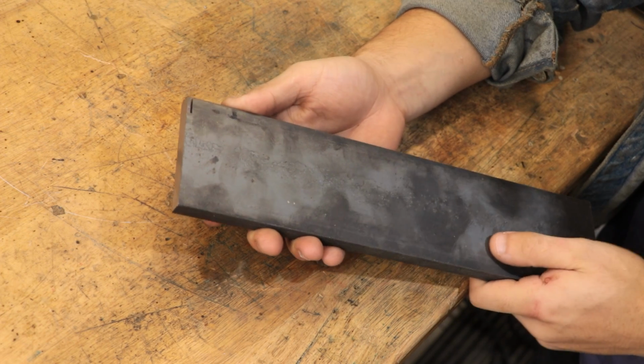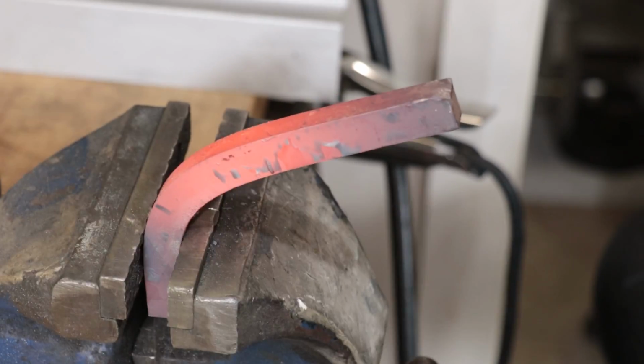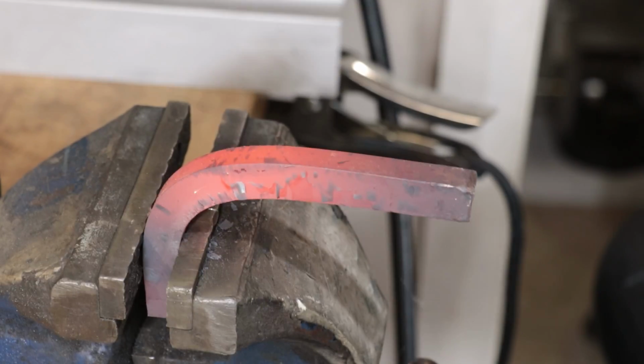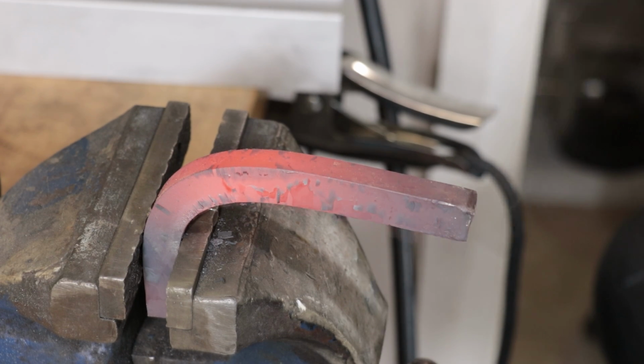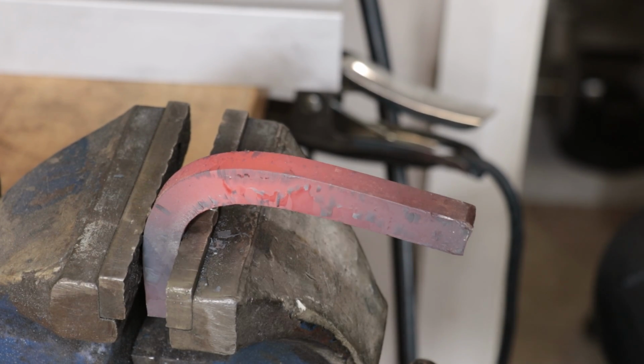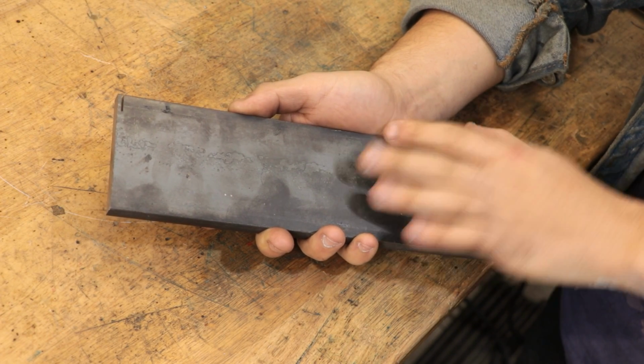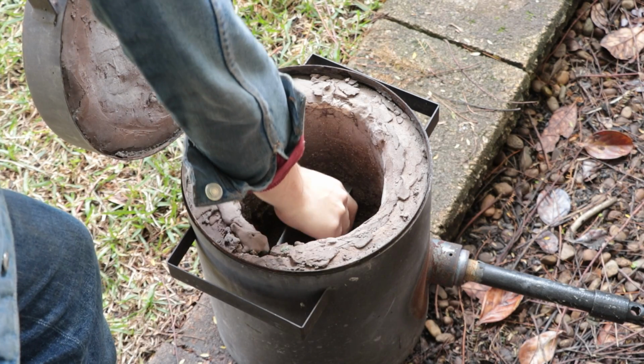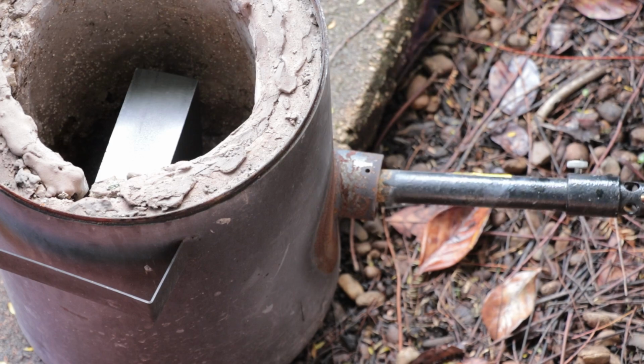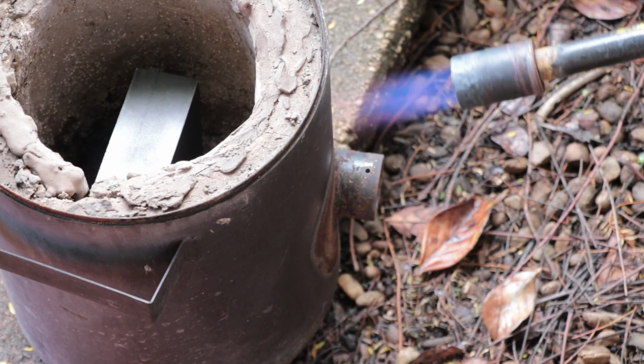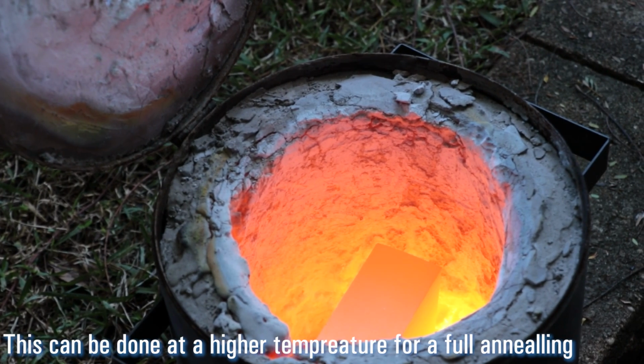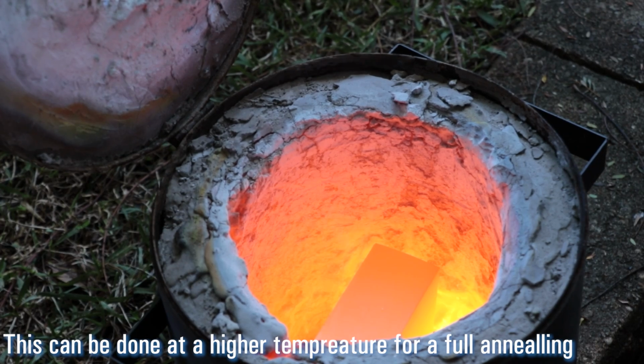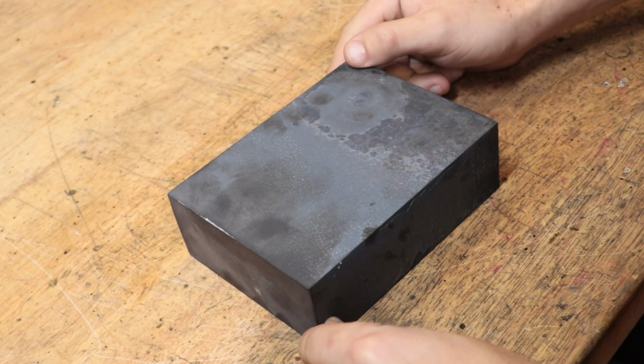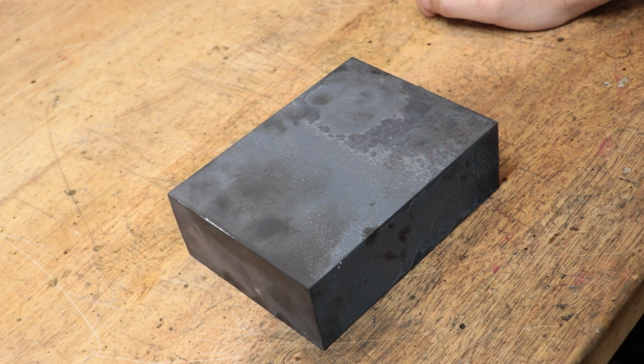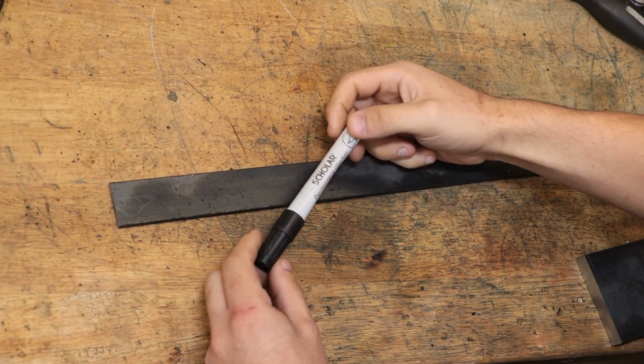Now, generally speaking, this shouldn't happen on steel that's been hot rolled, since the forming process takes place when the steel is red hot, above the recrystallization temperature, and as it slowly cools, it should leave it with a relatively stress-free, normalized microstructure. However, hot rolled steel isn't dimensionally accurate because it tends to shrink as it cools, so what a lot of people do is they'll take their cold rolled steel, which is dimensionally accurate, and put it in the furnace at about 500 to 600 degrees for a few hours, and that should relieve the stress. Doing that is effectively a reset button for the microstructure, and the resulting material shouldn't be stressed. You can also buy steel that's already been normalized in a furnace, although you are going to pay extra for that.